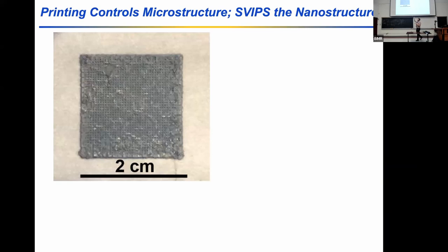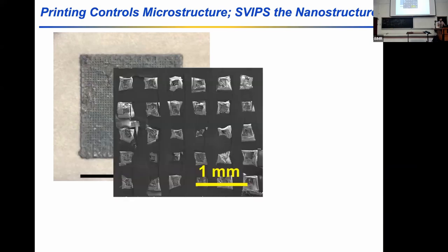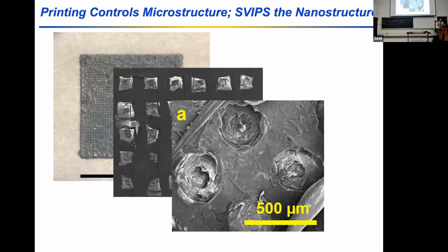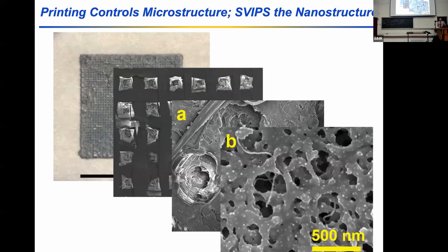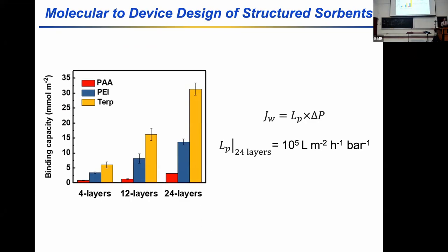Now we have some gray membrane because of the addition of the carbon nanotubes, but you can see the large flow channels that we've incorporated into these materials. And as we begin using a variety of microscopy techniques to look more and more closely, you can see the large flow channels with our filaments making up the structure of the filter. Getting closer, here's the large flow channel, and here's the filaments. And when we really zoom in to the nanostructure at a high magnification of the filament, you see a lone carbon nanotube sort of tracing through the material. But again, you see these polyacrylic acid nodules sitting on the surface. And so once again, these materials are able to be functionalized and capture copper from solution.